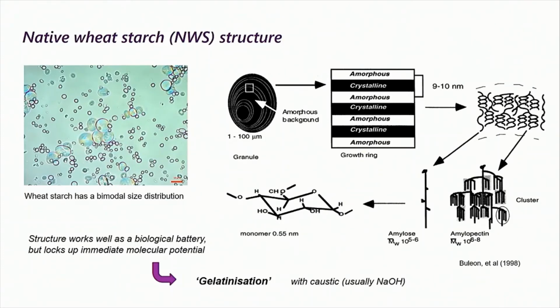But if we're going to use this in the flotation, we need to unlock those granules. You can see here that there's quite a complex structure. These molecules I just showed you on the page before are organised into this helical structure, and within that there are the amorphous and the crystalline regions. And so after all this, like I say there, it works well as a biological battery, but if you want to get the molecular potential of starch, you have to unravel these things.